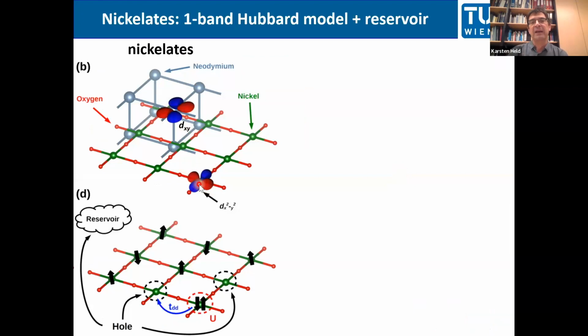You have the nickel x squared minus y squared orbital in the other plane, and so you have a positive and a negative overlap, and they cancel, so there is no hybridization. So if an electron is in the pocket, it will never go to the x squared minus y squared orbital. And because of that, we can consider these two systems as largely decoupled.